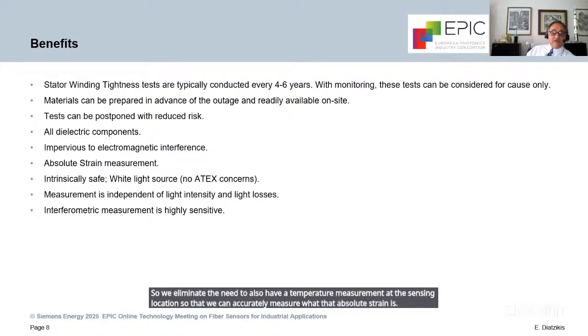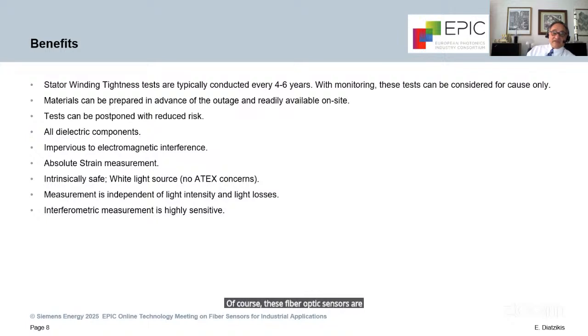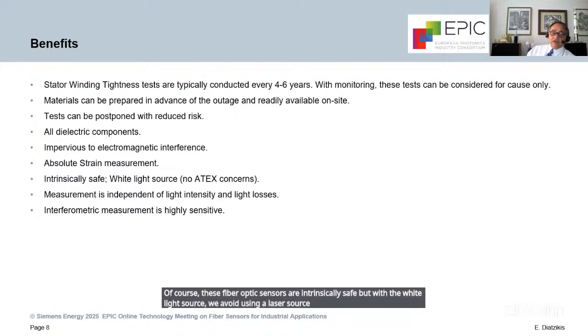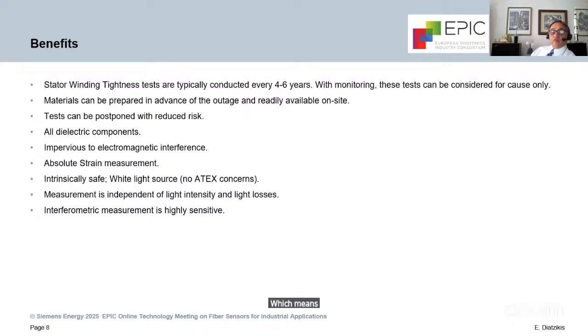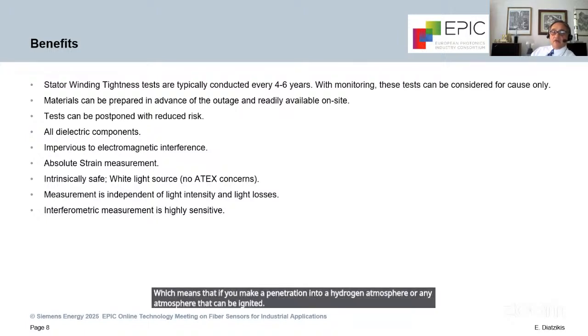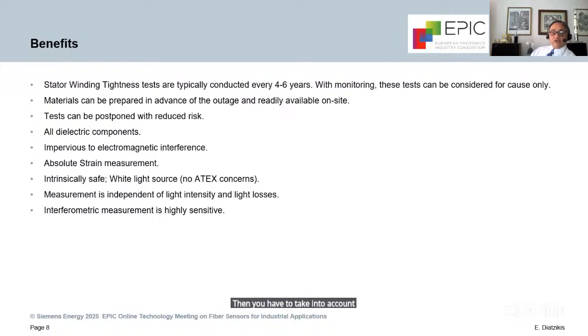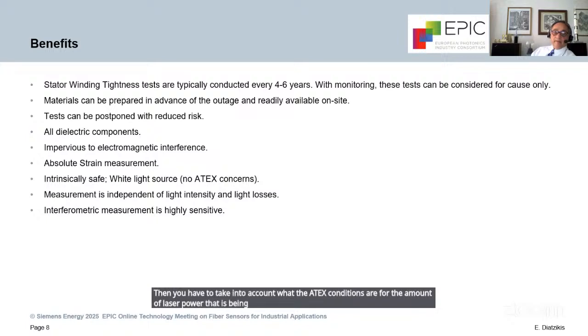Of course, these fiber optic sensors are intrinsically safe, but with the white light source, we avoid using a laser source, which in our industry means that we do not have any ATEX concerns. ATEX is an acronym for atmosphere explosive, which means that if you make a penetration into a hydrogen atmosphere or any atmosphere that can be ignited, then you have to take into account what the ATEX conditions are for the amount of laser power that is being transmitted through the penetration. For white light interferometry, that is not applicable.